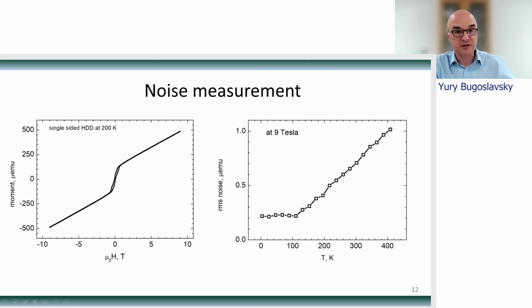So these were the calculations, that's the theory. Now let's compare it with what we can get in practice using our machine. And the experiment we set up is by using a thin film sample. The magnetization curve for that sample is shown in this left graph. The sample is a small fragment of hard disk drive. So the recording medium is a ferromagnetic film. It is deposited on aluminum substrate. So the ferromagnetic film produces a small hysteresis loop here at the center, and aluminum is paramagnetic, so it gives us this constant slope at higher fields.